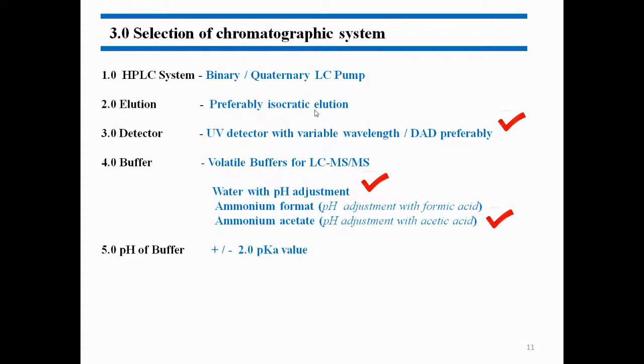But in the majority of cases, what happens is that you get polar degradants and non-polar degradants forming in the degradation study. In that case, isocratic elution fails to resolve these degradation products. So any binary system, even with a manual injector, will be fine. For academic research, I only suggest that if you do not have very high funding, please go to a basic binary system with a manual injector, without a column oven, preliminarily.